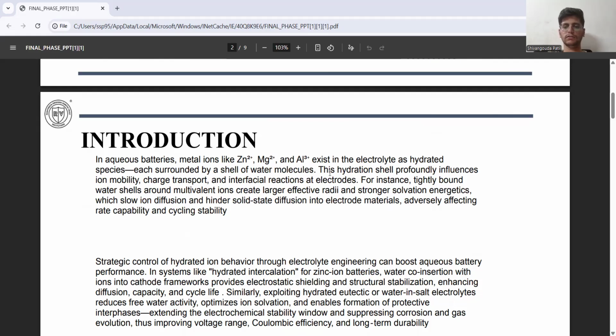For instance, tightly bound water shells around multivalent ions create larger effective radii and stronger solvation energetics, which slow ion diffusion and hinder solid state diffusion into electrode materials, adversely affecting rate capability and cycling stability.